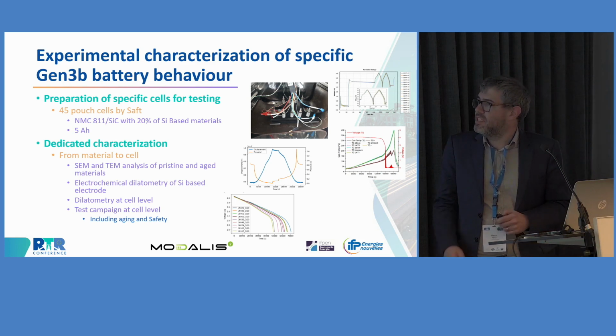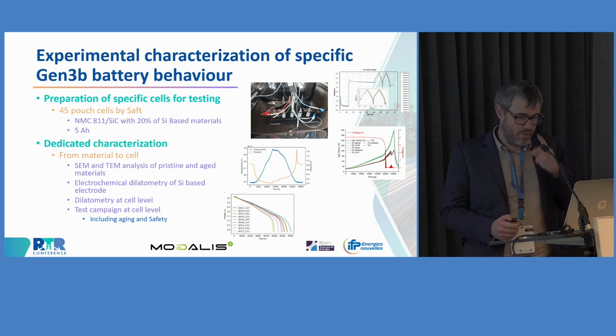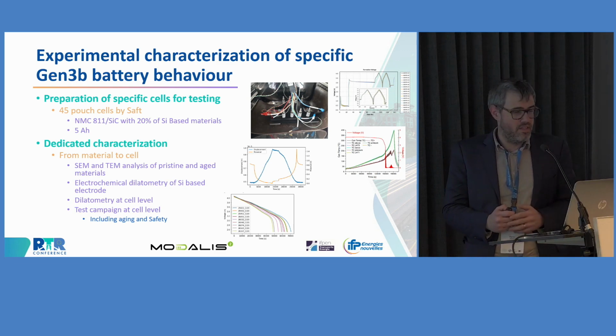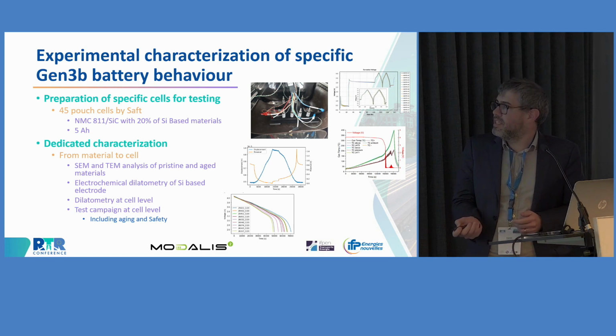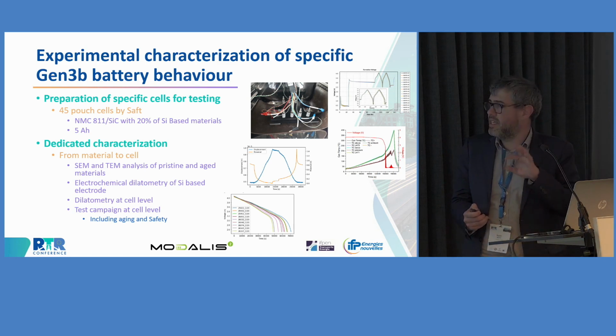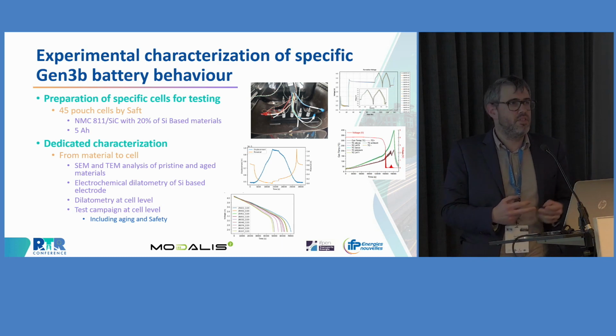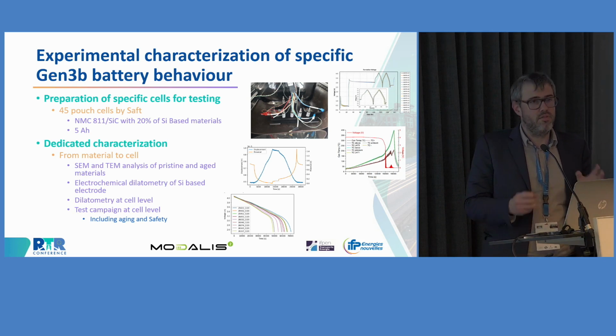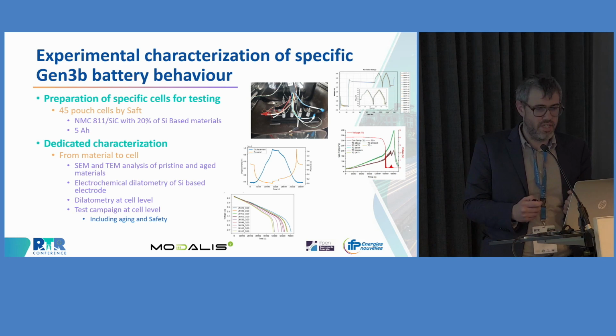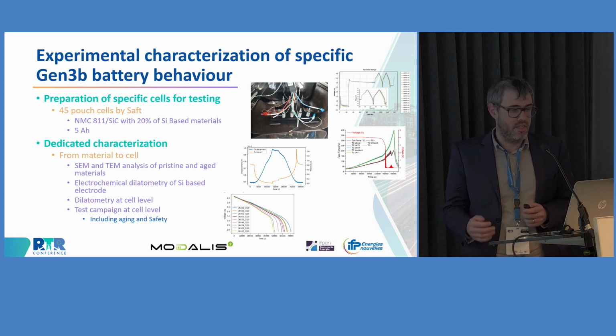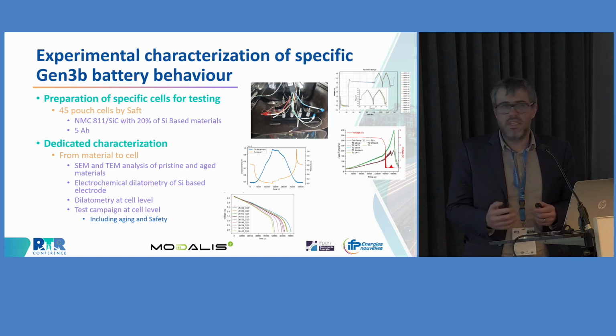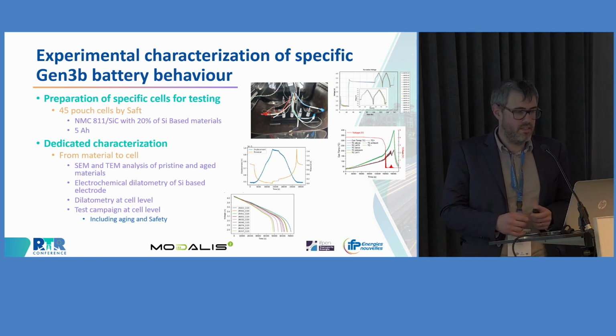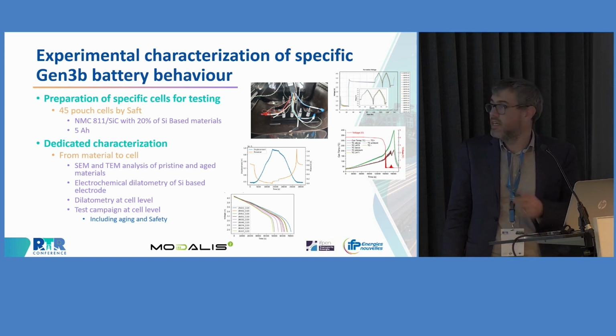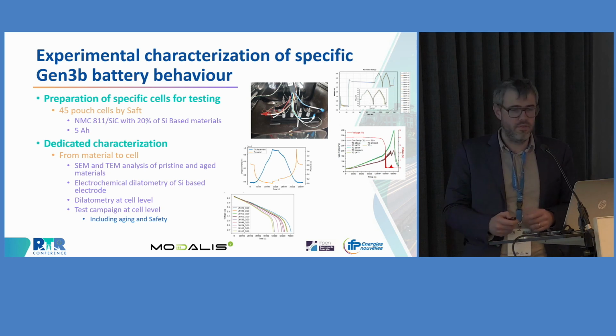So they were put into these jigs, and we made a test campaign on these cells in order to evaluate the aging, the nominal behavior, of course, and the safety of the cells. So you can see here, for instance, we did tests at cell level. Of course, we also had specific measurements done at the material level with TEM and SEM analysis to understand the way the material was working in the cell, and we also did some specific dilatometry tests in order to understand the mechanical behavior at the electrode level with an electrochemical dilatometer, and also at the cell level, where a specific cell dilatometer was developed by Siemens CT in order to see the behavior of the cell during cycling.